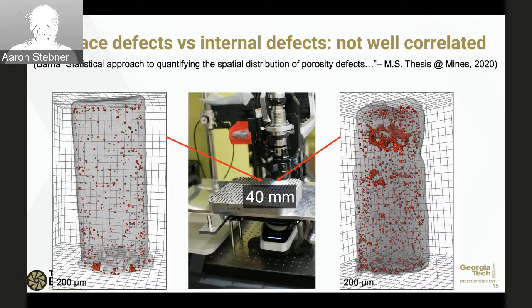And I didn't go through all the details here. There's a master's thesis published on this. The takeaway is the statistical correlations were not strong enough between the surface flaws and the internal features. So generally it was true that if you had a big nasty defect, you would also have a big nasty defect on the surface, but the inverse wasn't true. There were other things that could also cause surface defects, bad surface defects.